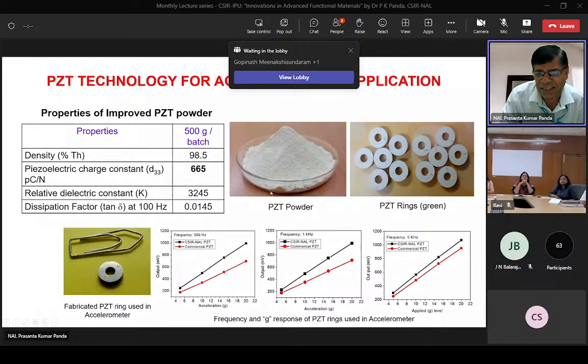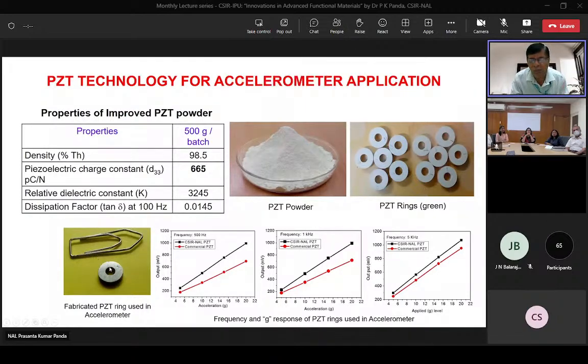The dielectric constant and dissipation factor loss are also very low. Using this powder you can make these PZT rings, and then they were tried at different frequencies: 500 Hz, 1 kilohertz and 5 kilohertz. In all the cases, you can see the NAL developed PZT was producing higher voltage, and the graph is totally linear compared to the commercial grade PZT.